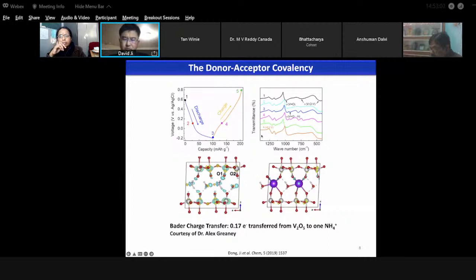And here we also observed charge transfer. That's something new. The charge transfer happens to the negative charges, the electrons, which are shared by V2O5 with the ammonium ion. So the ammonium ion is partially reduced, right? So the ammonium ion now is not +1. This is typical for lithium ion in graphite.